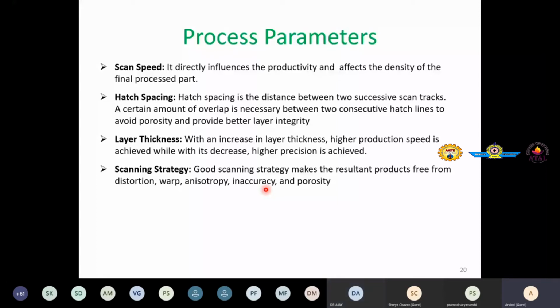So scan speed directly influences the productivity and affects the density of the final processed part. Hatch spacing is the distance between two successive scan tracks, and a certain amount of overlap is necessary between two consecutive hatch lines to avoid porosity and provide better layer integrity. Right? Layer thickness, with an increase in layer thickness, higher production speed is achieved, while with a decrease, higher precision is achieved. This is what I just mentioned.